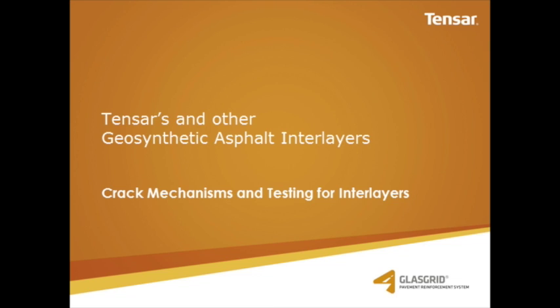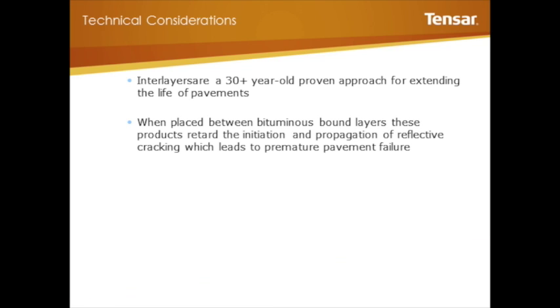So when you're evaluating data to use different materials, take that into consideration, because most of the testing that we do today on materials is associated with fatigue cracking. There's very few standardized tests for reflective cracking. But keep that in mind. Strain levels are significant, an order of magnitude difference. And the other thing is, remember I told you about low temperature and age. The low temperature performance is of greater significance because your fracture performance is more at risk.